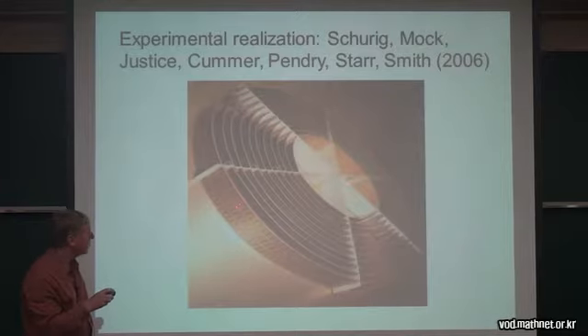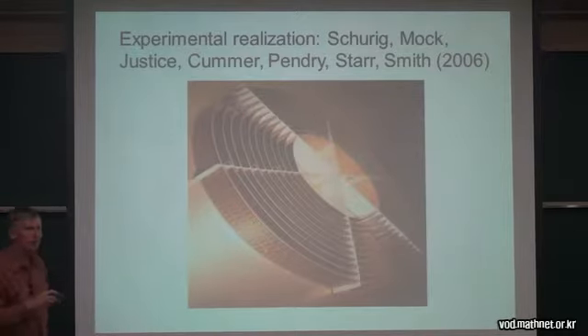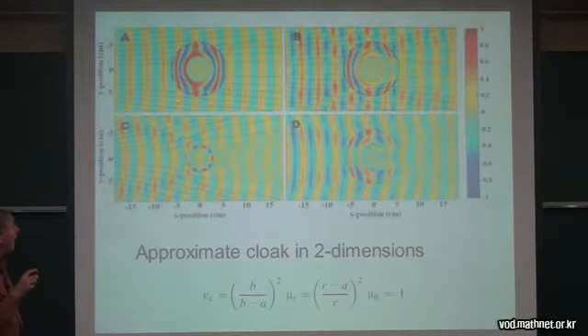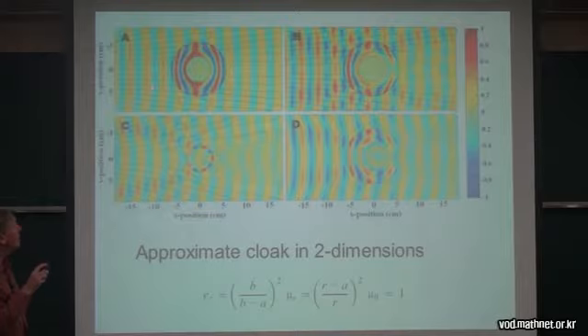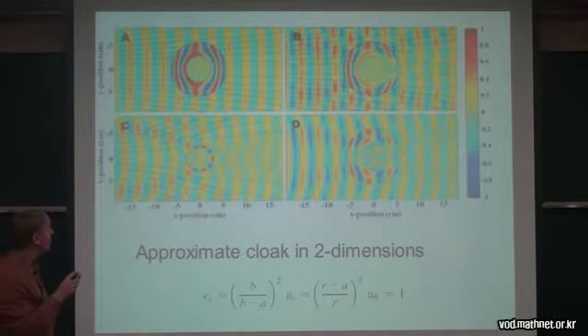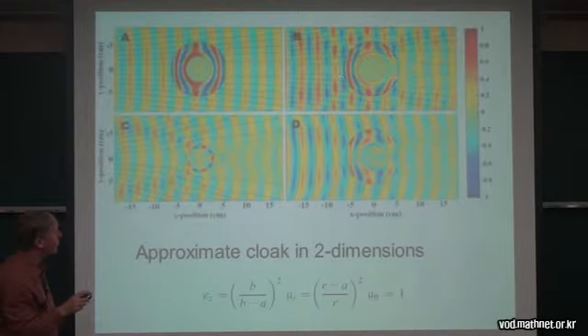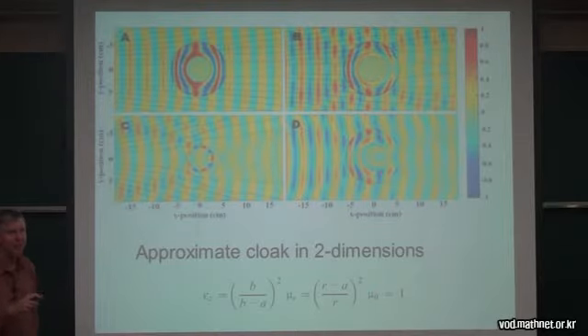So here, again, is this split ring resonator type structure. And these are the experimental results, and this is the numerical results. This is the ideal cloak, showing the waves not penetrating the material inside, but passing around the cloak. And unfortunately, this sort of cloak is difficult to achieve in practice, and so they actually had a modified cloak which had the property that in the geometric optics limit for rays it would behave in an ideal manner.